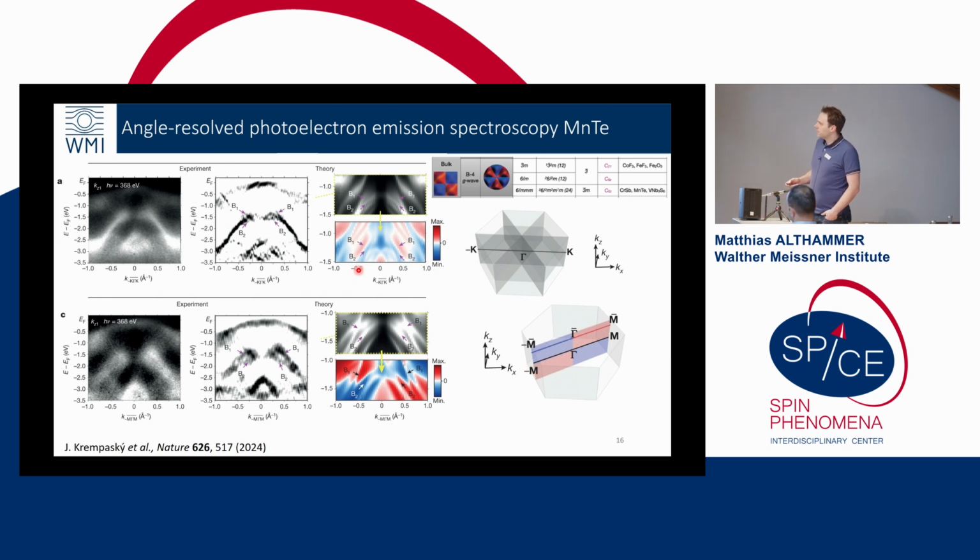And you have now here the experimental structure. In one case, you see it down here, it says that it is in the K direction where you're looking at, and you see only a very vanishingly small splitting, which also nicely agrees with the theory calculations that are depicted over here, that also take into account spin-orbit effects in these structures.